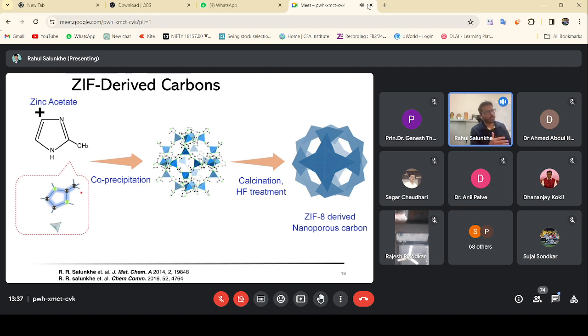But for today, we are just starting with the simple ZIF-8 derived nanoporous carbon, which is very simple and very commonly used, and it has a very stable porous structure. ZIF-8 and ZIF-67 have a highly stabilized porous structure, so the porous structure does not collapse. When we use it in the electrolyte system, the porous structure should not collapse, and this is a typical requirement of any application. That's why ZIF-8 and ZIF-67 are the most commonly used nanoporous carbon materials.